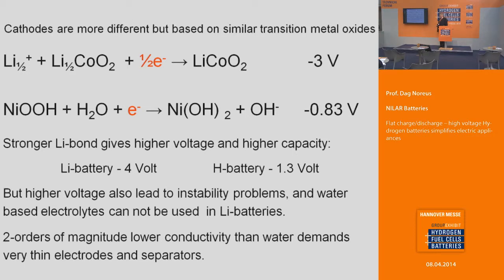But it also gives a lot of problems, because the high voltage creates a lot of side reactions that are difficult to control. We can see that also in the cathode reactions. When we discharge the battery, we can only get half an electron here, because you cannot remove all the lithium from the cobalt oxide, because then it will decompose and release oxygen. So the difference is not scaled 4 to 1.3 here, because the capacity of the cathode is more effective in the metal hydride battery.